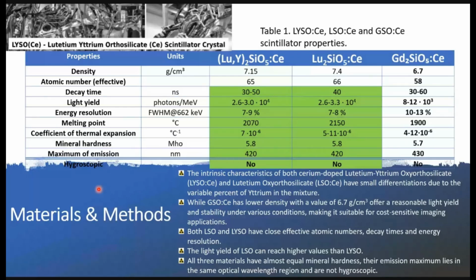In the first table, we can see the internal properties of these three scintillators. We can see that the two oxyorthosilicates, the lutetium and the lutetium-yttrium, have similar density and effective atomic numbers. Also, their decay time is in the same region, as we can see here. However, the addition of yttrium in the mixture results in a little bit lower light yield compared to the initial material. Furthermore, their energy resolution is in the same range. They both melt at similar temperatures. They have equal hardness, and they both emit light in the same wavelengths.